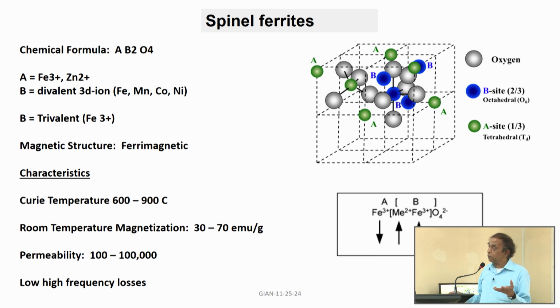So, any device you make with spinel ferrites can work at much higher temperature compared to other choices such as iron, cobalt and nickel. If you go to very high temperature, metals get oxidized and go bad, whereas these are already oxides, they have pretty good Curie temperature, and you don't have to worry about oxidizing any metal. Okay. And they have decent magnetization at room temperature. Permeability is anywhere from 100 to 100,000, especially manganese ferrite, it has very high permeability.